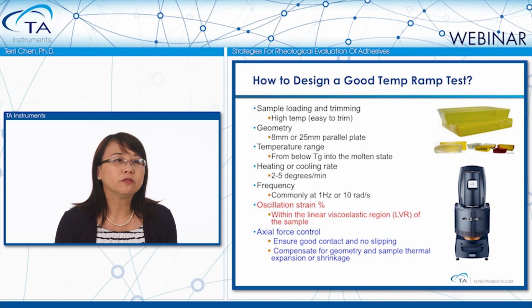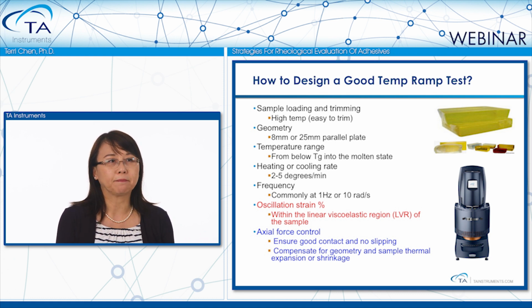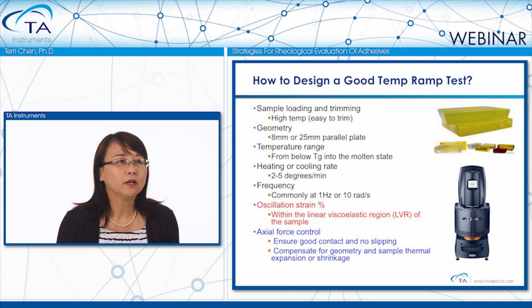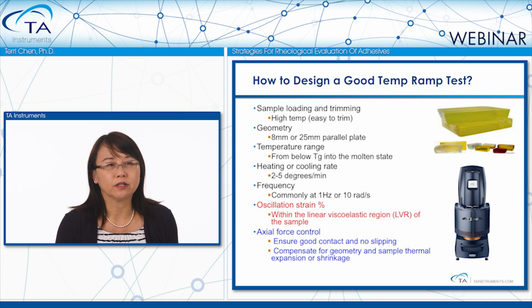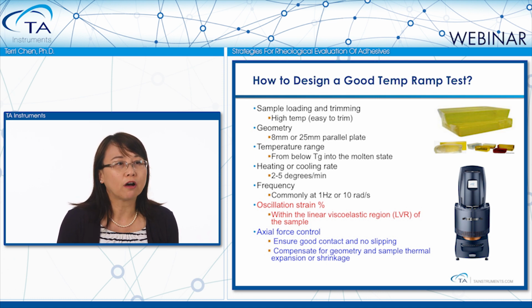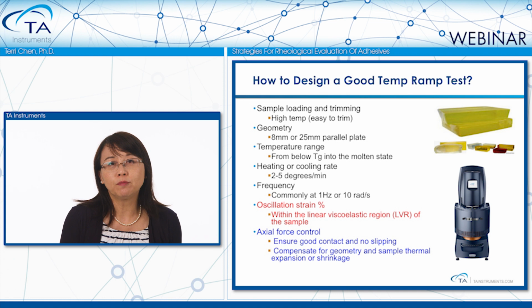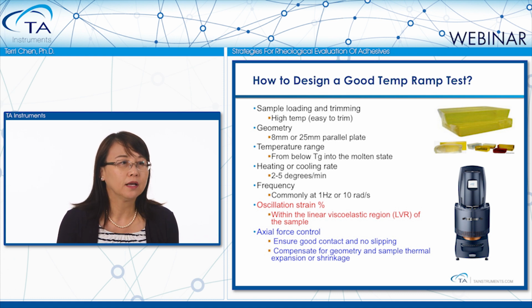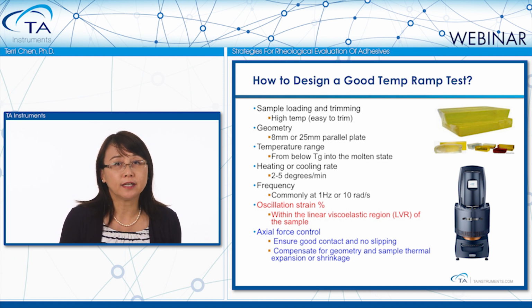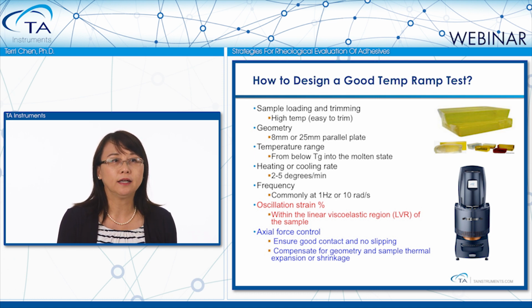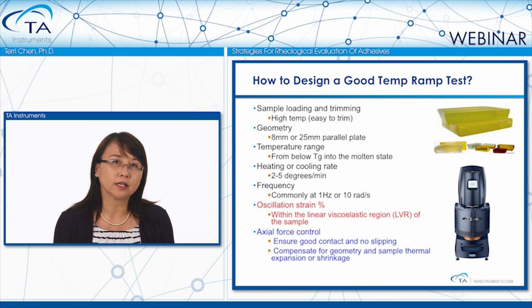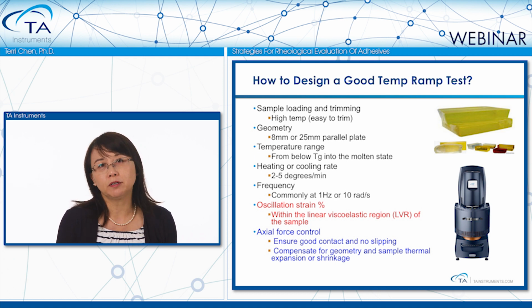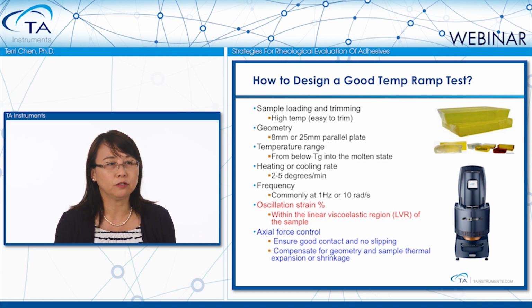Here, I would like to introduce some guidance for a good temperature ramp experimental design. First of all, it is always good to load the sample at higher temperatures because the sample will be soft or molten so that it will be easy to trim. The most commonly used geometry for testing a PSA sample is the 8mm parallel plate. If you do not intend to go through glass transition, a 25mm plate is also okay to be used.